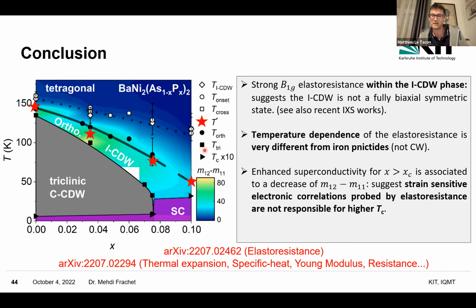So we literally have a 1 or 2 Kelvin difference between the temperature at which we see a feature which we can call a Bragg peak, which is really resolution limited and shooting up in intensity, and 2 Kelvin below we see the small distortion in the expansion. We also see it in the X-rays, as I showed in my talk. There's a broadening and a kind of splitting of the high index peaks. Michel has been doing a full refinement of the structure in the orthorhombic phase using the orthorhombic setting.